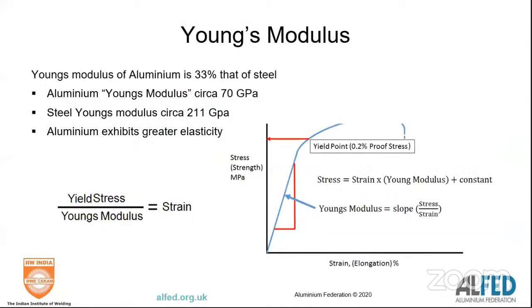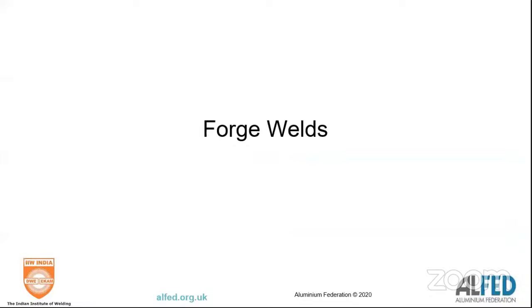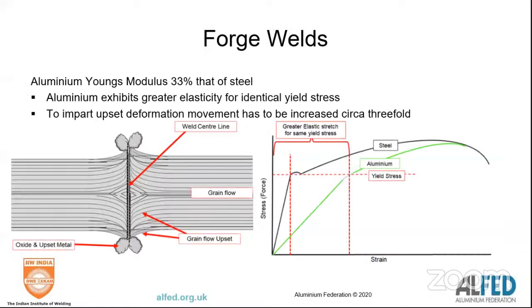Aluminium's actually got a low Young's modulus. It's about 1/3 that of steel. So although we can match the yield strength and the tensile strength of a lot of alloys, it is far more elastic. And that elasticity means that when you're doing things like forge welds, you've got to do a lot more effort. So in a typical forge weld where you want to upset, you would need to put in about 3 times more upset deformation to achieve a forge weld in aluminium because of its low Young's modulus, because of its high elasticity. It's very, very springy.